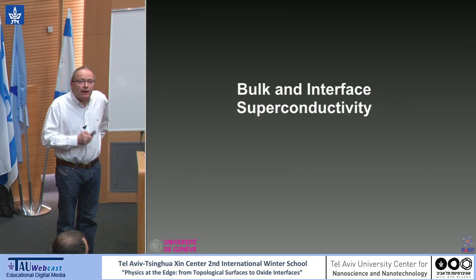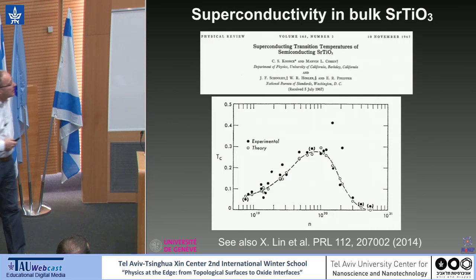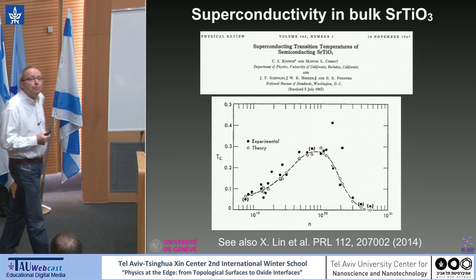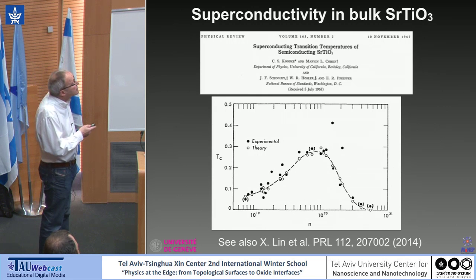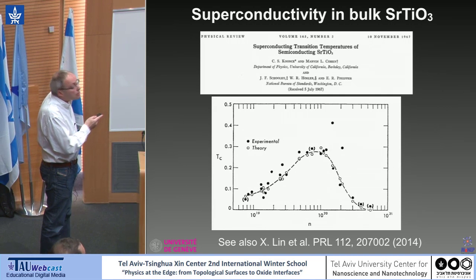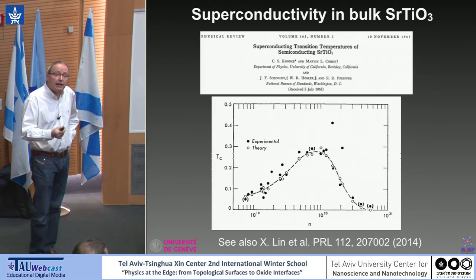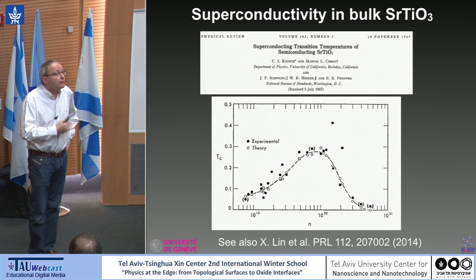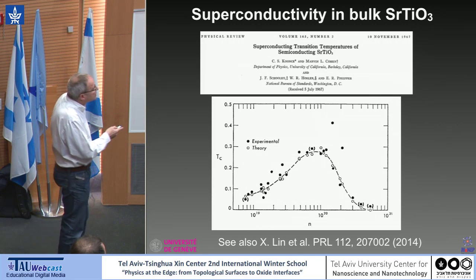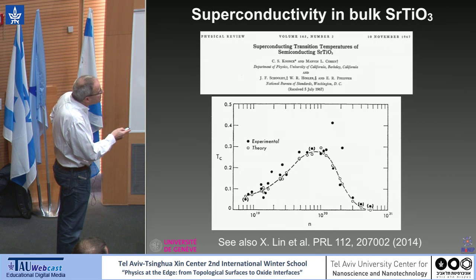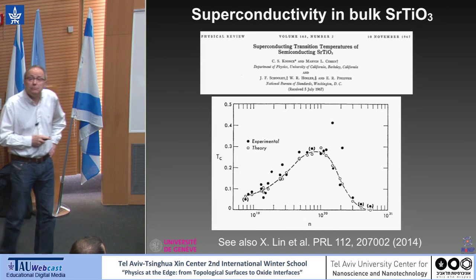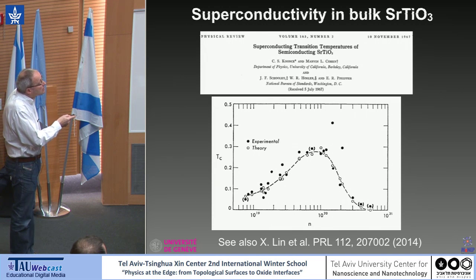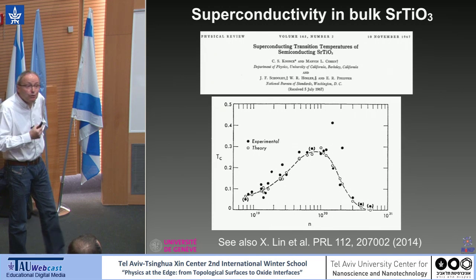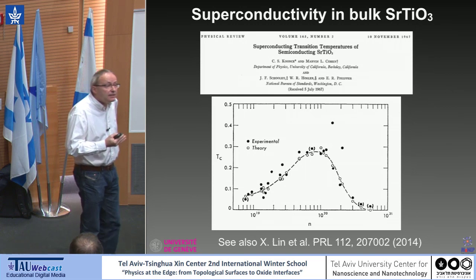Now there's one thing which is very important, and many of you know this. Strontium titanate can be doped and is superconducting, bulk strontium titanate. What you can do is replace strontium by lanthanum, titanium by niobium, or you can remove oxygen. If you do this, the system is superconducting, and you see here results from 67. TC is going up and TC is going down. So you see a dome, and max TC is about 0.3 K. So it looks very much like what we see at the interface.